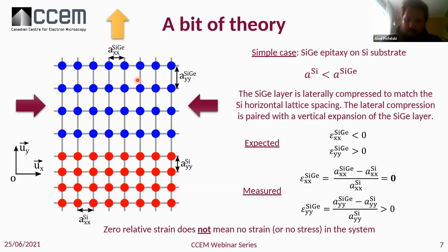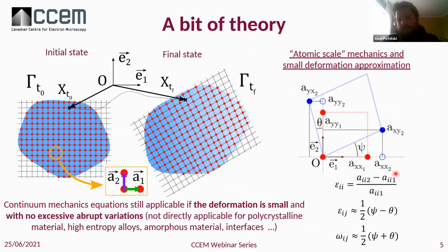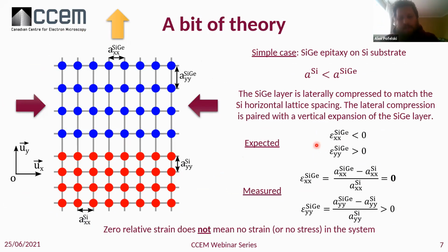So what we expect if we talk about strain is that we have a negative strain, like a compression, laterally. So this epsilon xx negative and this epsilon yy positive. The problem is that if we do this measurement now using the equations that have been just shown before, now we have a different story, because if you measure the lattice parameter of the silicon germanium in comparison to silicon, we will find that laterally we have a zero. So like the very kind of shocking type of result, saying that I have a zero strain, but technically there is a compressive strain. And that's the problem of this relative strain characterization method in the interpretation, is that we don't compare to the relaxed state of the silicon germanium, we compare it to the silicon lattice underneath.